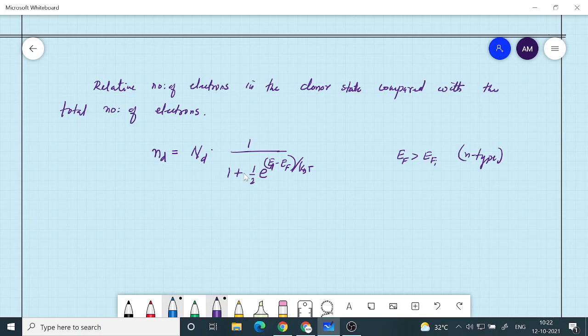Now there are some electrons in the conduction band. I can again do the Boltzmann approximation, and neglect this one with respect to the second term. Why? Because I will assume that Ed minus Ef is greater than 3 kBT. Then I can do the Boltzmann approximation. This is also a valid assumption, because Ed is a level very close to the bottom of the conduction band, and if Ef is sufficiently below the conduction band, this requires only 3 kBT, and this can easily be achieved for low level doping.